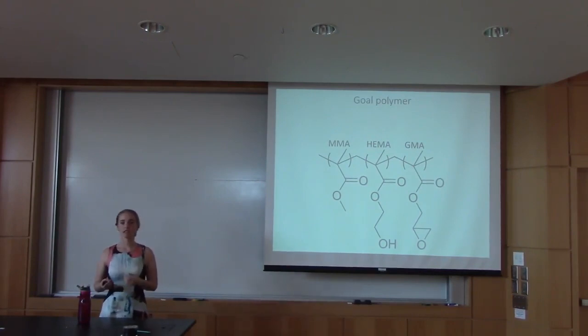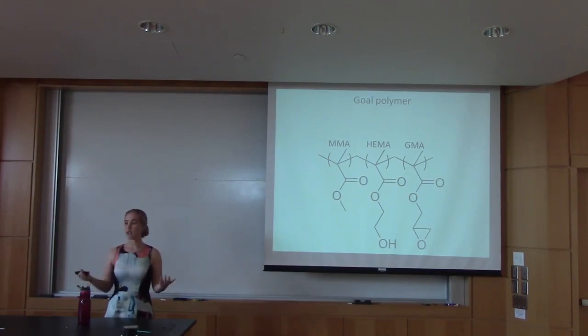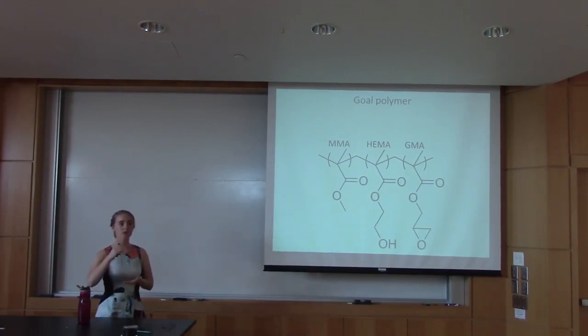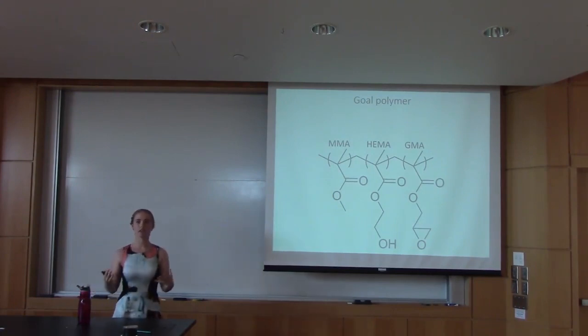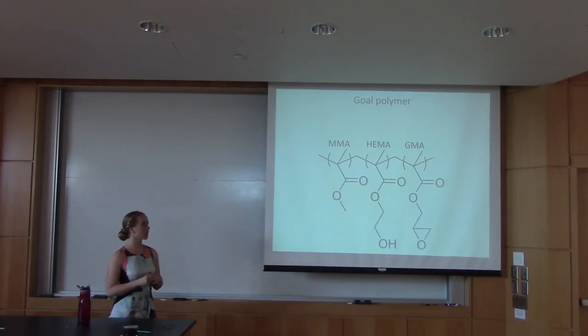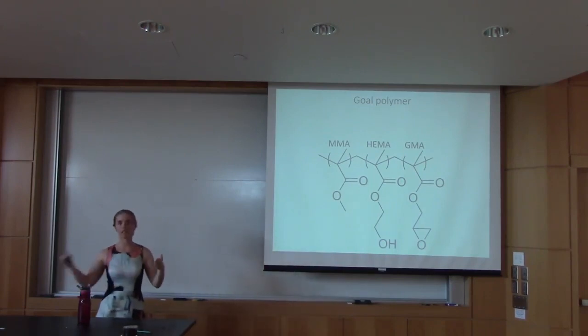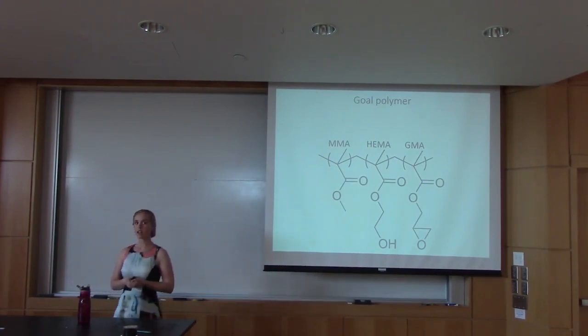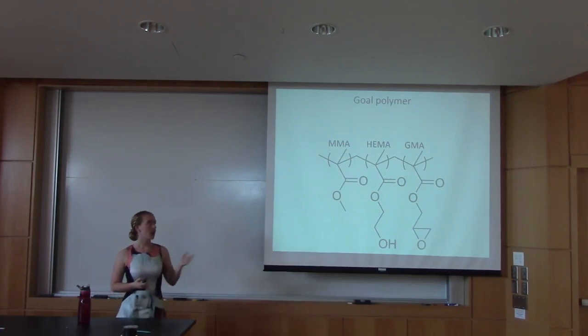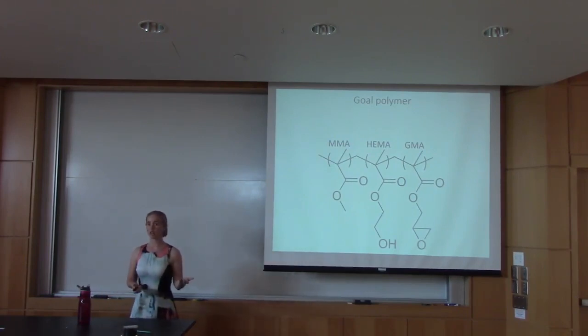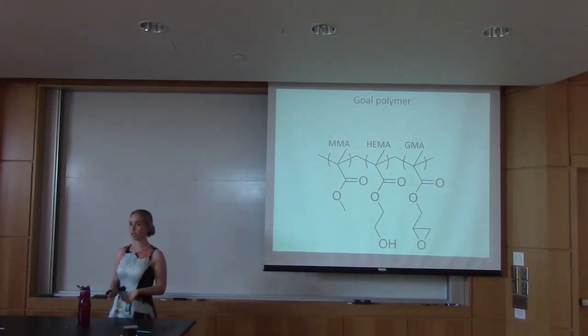And what a crosslinker does is, when we are making these random copolymer strands, there's more than one strand in the solution. And we want them to be connected to each other and to make a coherent solid and have a coherent surface. And so what this GMA does is it connects those individual strands. So our MMA and our HEMA are our main components that affect our hydrophobicity and hydrophilicity. And the OH at the bottom of our HEMA makes it more hydrophilic than the MMA, which does not have this OH, and so that is more hydrophobic.